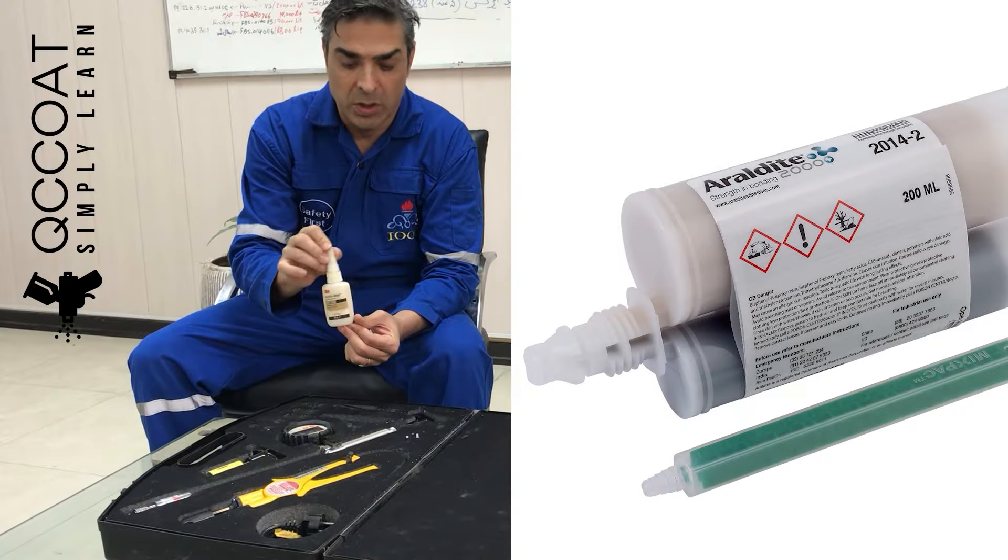Cutting device. The amount of adhesion is strongly dependent on the surface, and it varies with the change of the area. So that only the bottom surface of the dolly participates in the test, and the paint around the dolly does not affect the results, this device is designed to cut around the dolly, and only the bottom surface of the dolly is affected by the test.